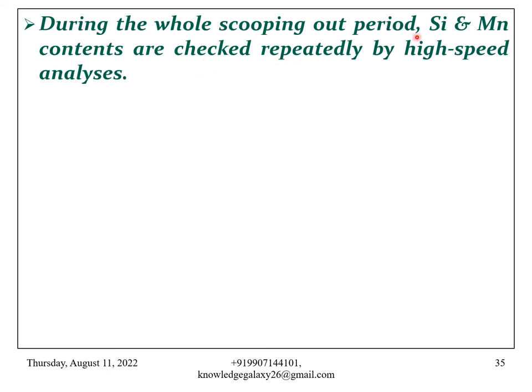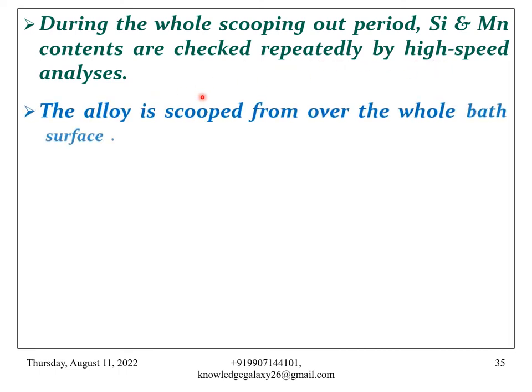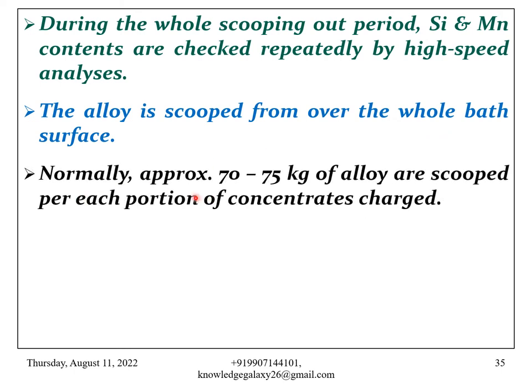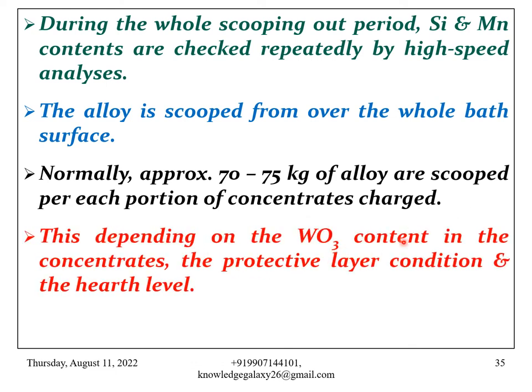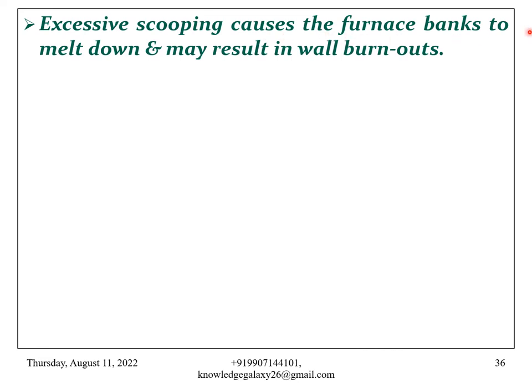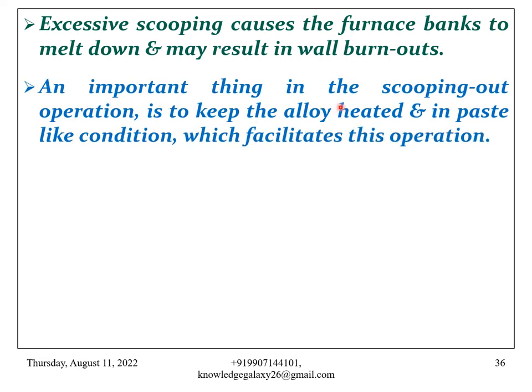During the whole scooping out period, silicon and manganese contents are checked repeatedly by high speed analysis. The alloy is scooped from over the whole bath surface. Normally, approximately 70 to 75 kg of alloy are scooped per each portion of concentrates charged. This depends on the WO3 content in the concentrates, the protective layer condition and the hearth level. Excessive scooping causes the furnace banks to melt down and may result in wall burnouts. An important thing in the scooping out operation is to keep the alloy heated and in paste-like condition, which facilitates this operation.